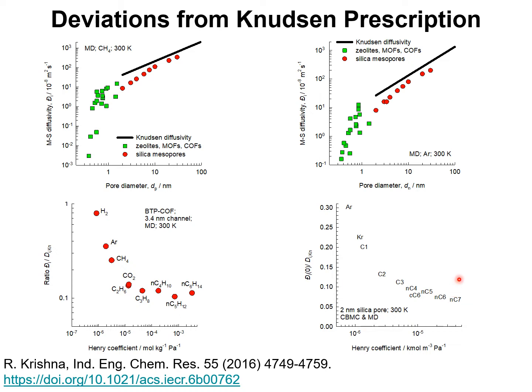The takeaway message from this video presentation is that the Knudsen diffusivity formula is applicable for poorly adsorbed gas molecules, and with increased strength of adsorption, the deviation from the Knudsen formula increases. Further details are available in my publication from 2016.